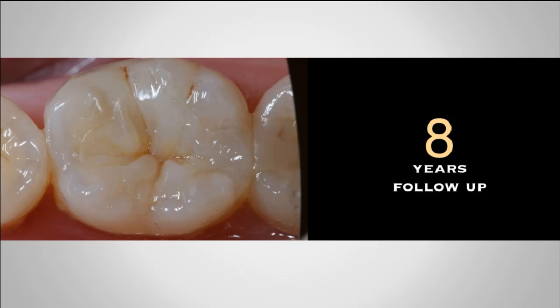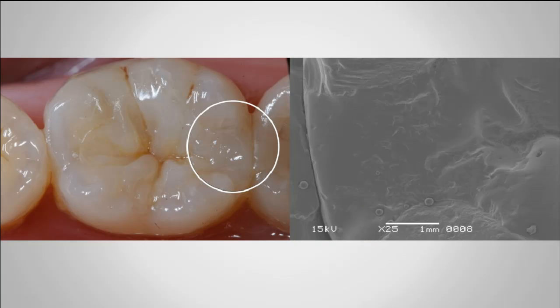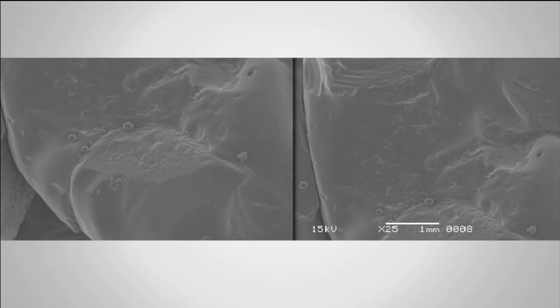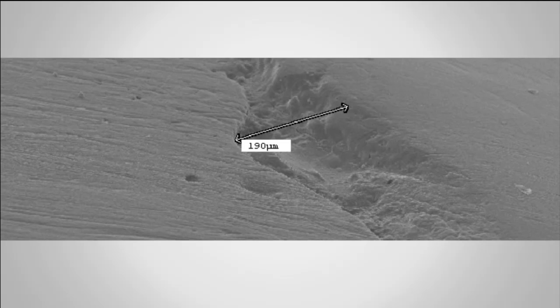And if you see this composite under the SEM, I can see that you already have abrasion of the composite. You have some changes on the surface and also the interface. But if you look at the natural tooth, I can see that as well. And if you pay attention, the interface is still sealed.